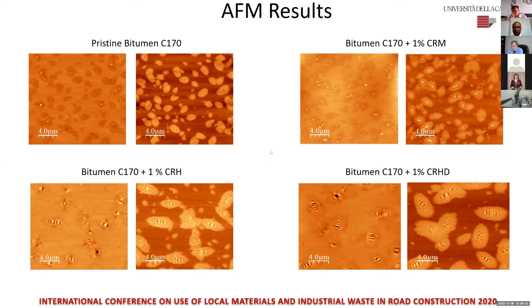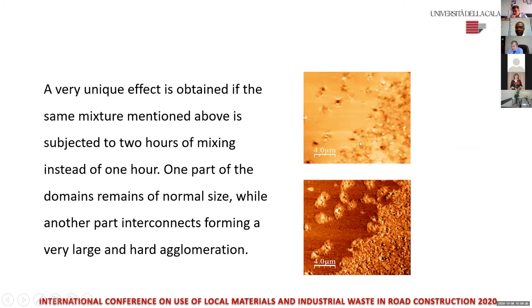Now, we analyzed the samples that we left for 2 hours. Remember, I told you that we also prepared some samples for 2 hours just to see if it would improve. When we checked under the atomic force microscope the ones we used for 2 hours, the asphaltenes were not in optimal condition because they became very hard. The domains remained of normal size, but they became very large and hard. They agglomerated together, they fused together to form this agglomeration, which makes it hard and maybe makes it easier to break. So it means that 1 hour of agitation is the optimum time for the preparation of samples.